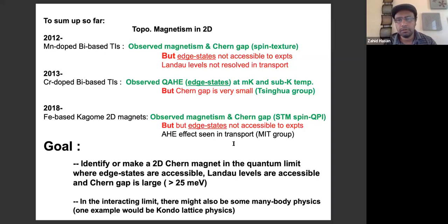So to sum up, what I think the goal is: identify or make a 2D Chern magnet in the quantum limit where edge states are accessible. I mean, it may be theoretically there, but if experimentally you don't access it, it's not fun. Landau levels are accessible and the Chern gap is large, I would say at least more than 25 millivolts. And also in an interacting limit, there should be some many-body physics, like twisted bilayer graphene led to some many-body physics. Later on, I will show that some of the Chern magnets do have intrinsic many-body physics, like Kondo lattice type physics, if I have time. So this is the holy grail